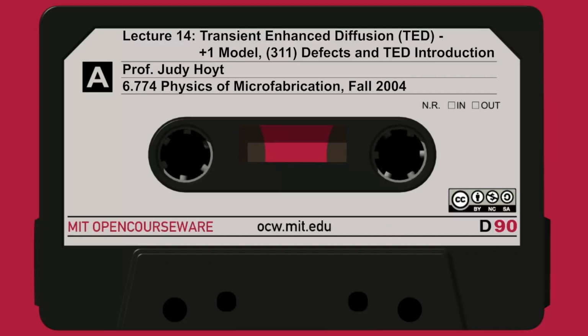And this was another interesting one, on the bottom panel. This was a sample where it was just annealed at 850 for 10 seconds, but there was a very high concentration of oxygen, background oxygen, in the sample. In fact, the oxygen in the sample was about 10 to the 20. So during the epitaxial growth, the silicon germanium layer was accidentally doped with oxygen, was not really high purity material. And interestingly, TED is completely eliminated in the presence of a very high concentration of oxygen. In fact, you can see these plus signs are the boron profile on a sample annealed, again, 850 10 seconds, same RTA.